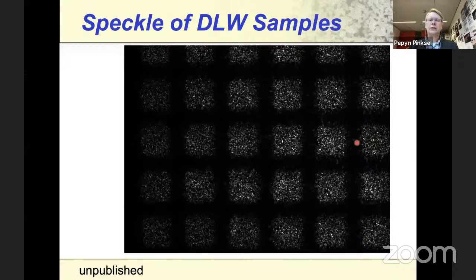If you look at many of these nominally identical cubes, and we shine light on it in the same way, then you would expect the speckle patterns to be the same. Obviously, they're not. This means that there are fabrication issues, even with such a small deterministic sample as we did here.